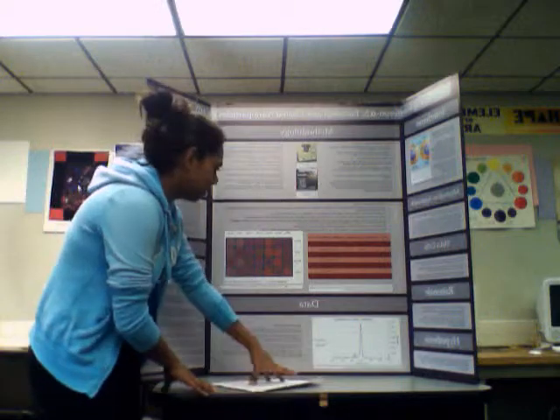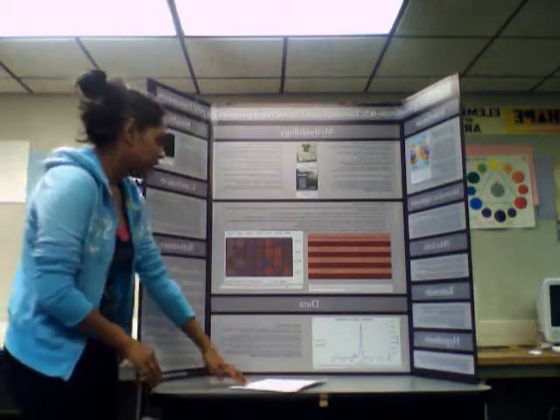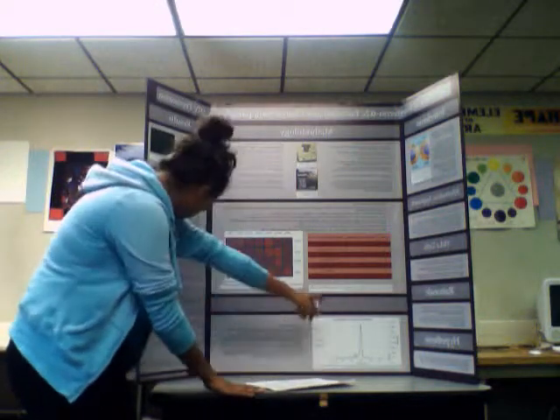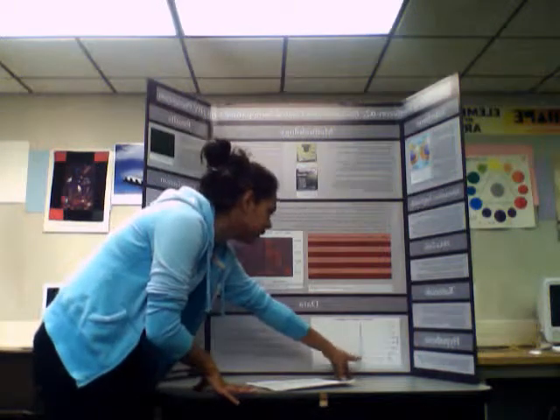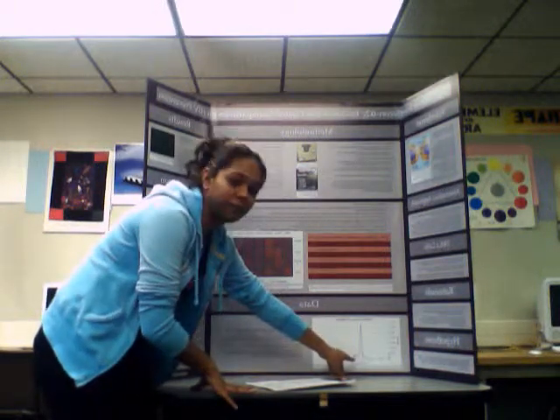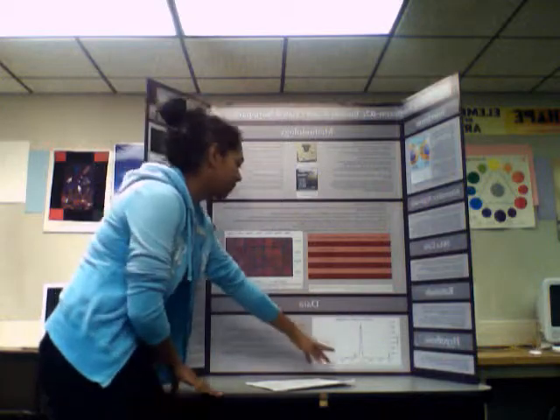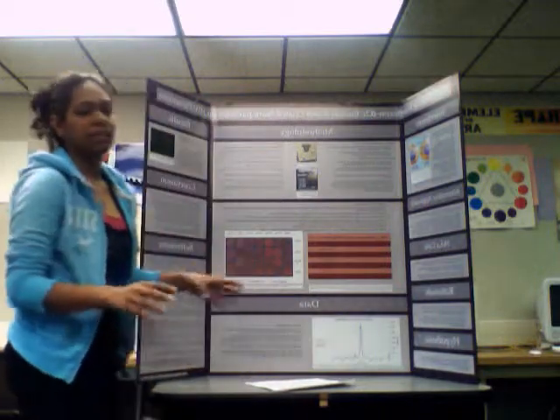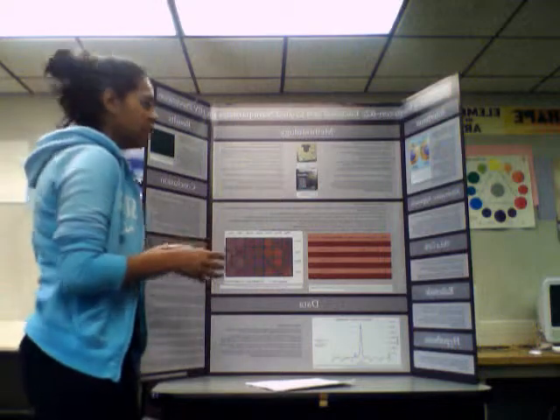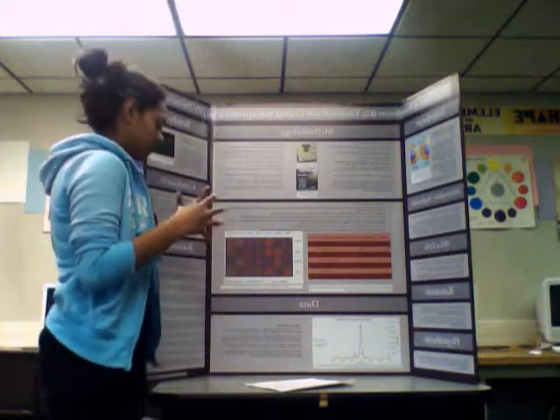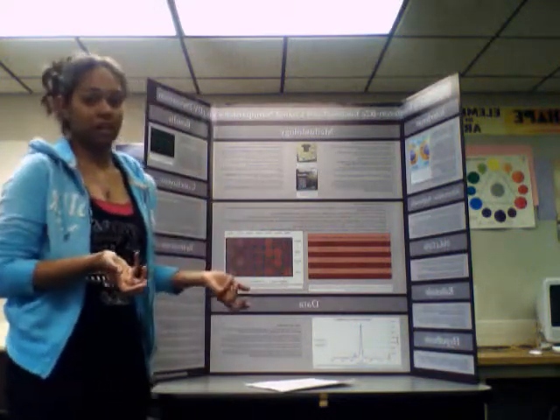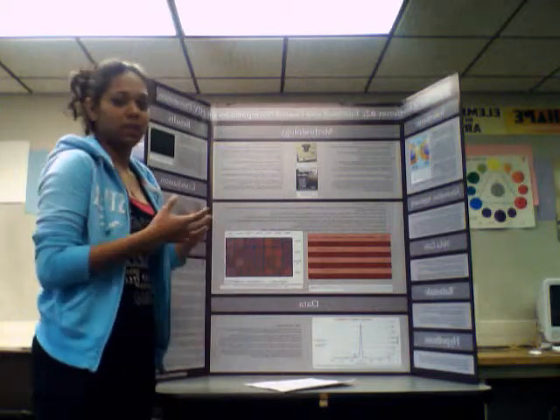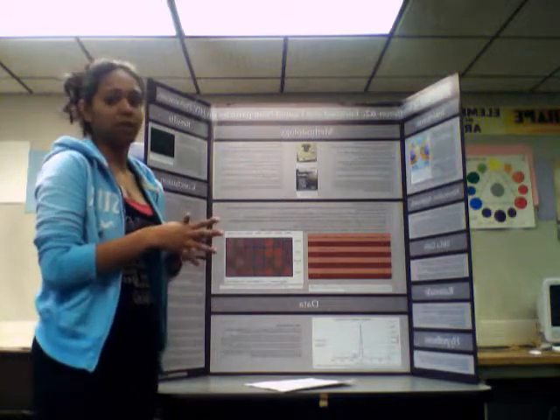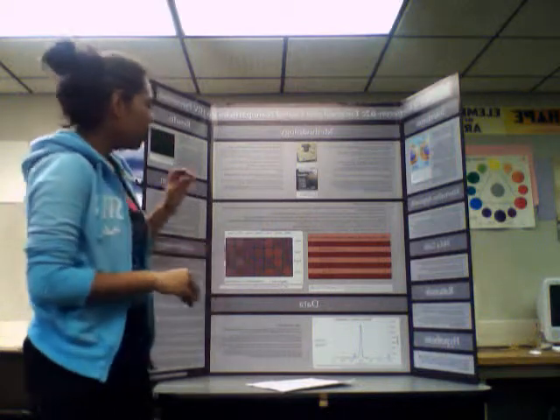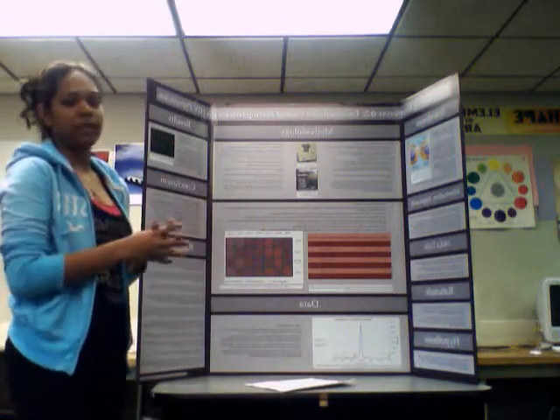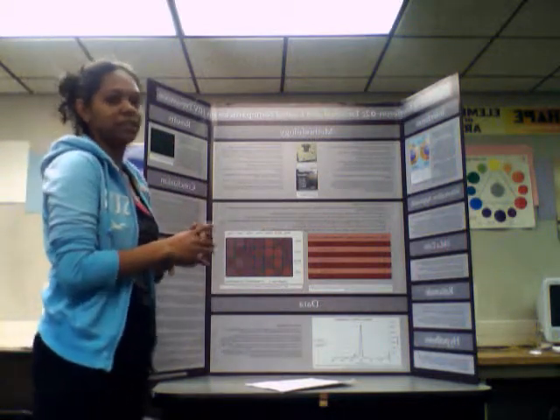Bringing your attention down here is showing the results of the samples. So as you can see, at 30 minutes, there's an absence of a peak for the interferon nanoparticle supernatant. This shows that there are actually nanoparticles present in the columns, which means that the interferon has effectively coated the nanoparticles. This means that I was successful in coating the actual surface of the nanoparticles with interferon. Upon establishing that, the sample was then again placed in -80 degrees Celsius for storage.